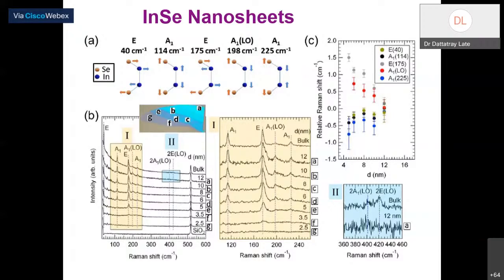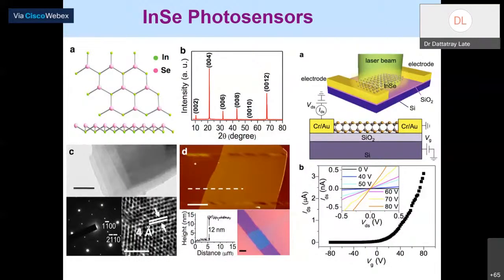But we found the origin of why the spectra disappear. You know, at 3.5 nanometer level, or maybe at 3 layers of this indium selenide, the bonding between indium and selenium becomes so weak that it does not allow you to collect the spectra. The bonding is so weak, we are not able to collect the spectra. And this is also a very good material for gas sensing application, sensor application, photo detector application.